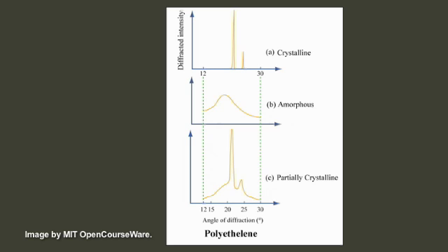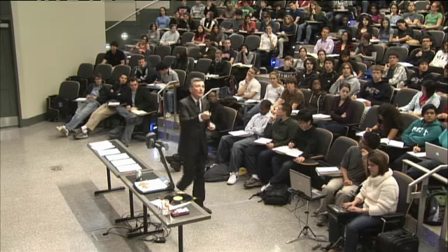Okay, so now here's some X-ray diffraction. So this is crystalline, where they've zoomed in on one of these zones, and they've just gotten the diffraction pattern from that zone, and you see Bragg peaks. And then this is in the amorphous region. It's not featureless. There's one broad peak. Why one broad peak? Because even though there's no long-range order, you have short-range order. You know that you've got a carbon on either side, you've got hydrogens and so on. So that short-range order gives you the broad peak.